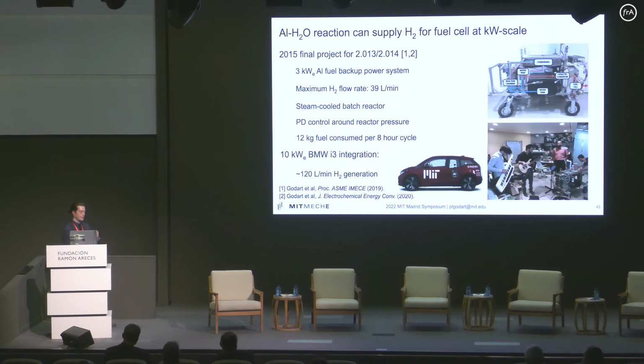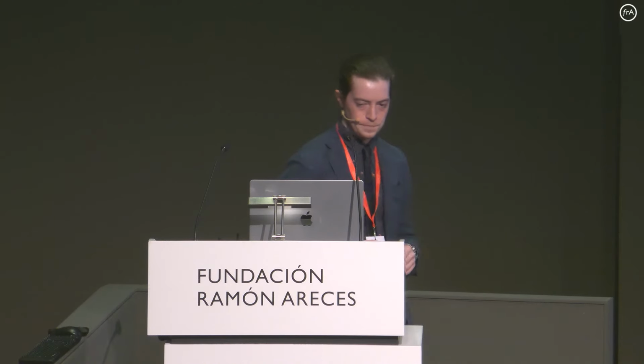It's very easy to control this reaction because all of that surface area that opens up when you start the reaction, as the aluminum disintegrates, means that the reaction dynamics are very fast. So it responds almost immediately to small changes in water flow rate into the reactor. So it's very easy to control. We were just using a simple proportional derivative controller for this.